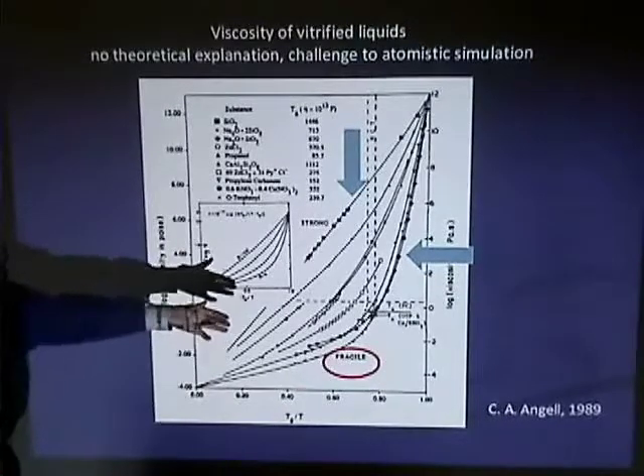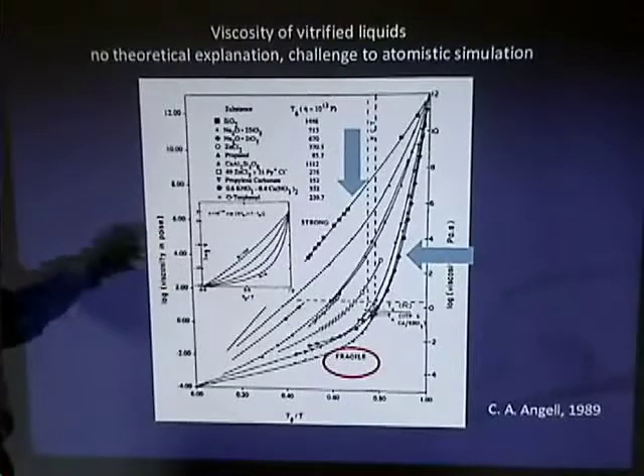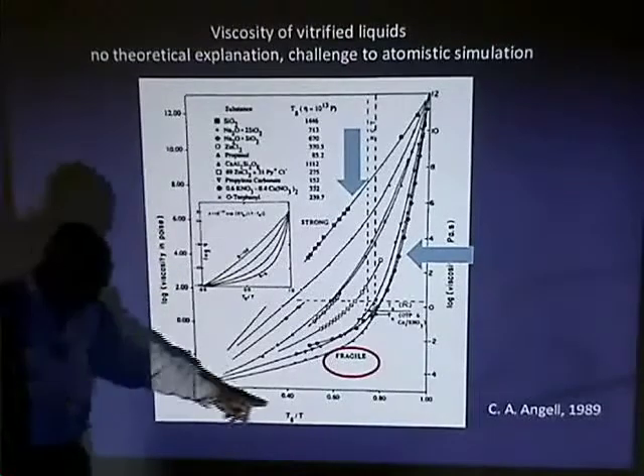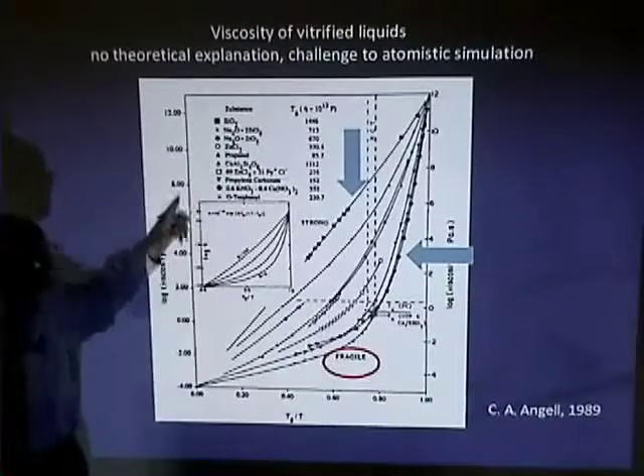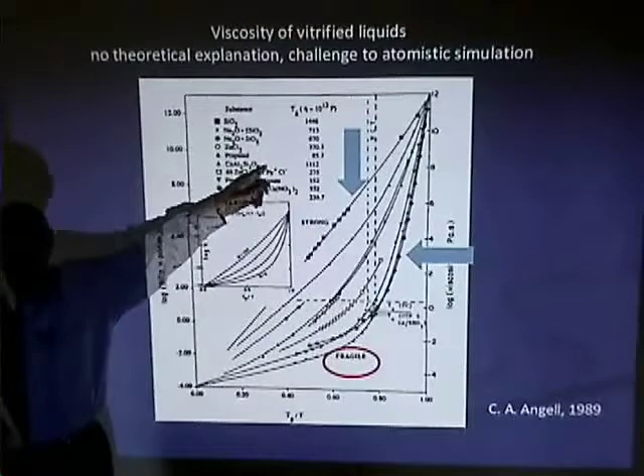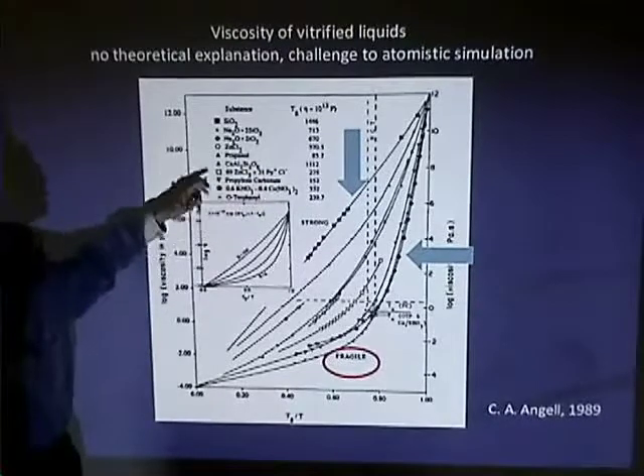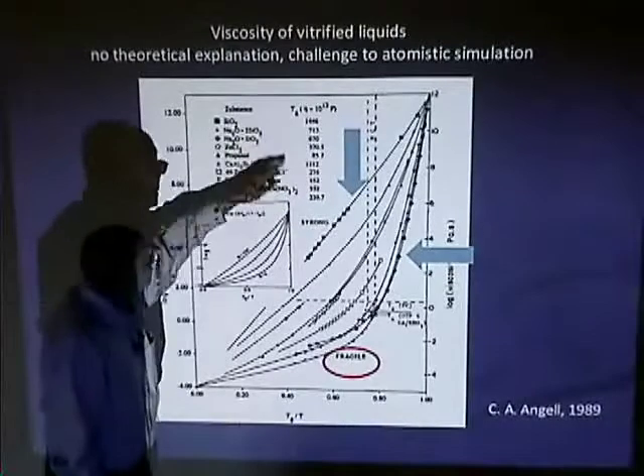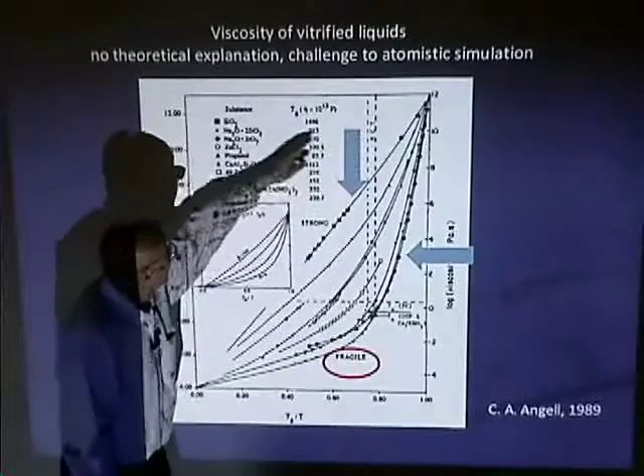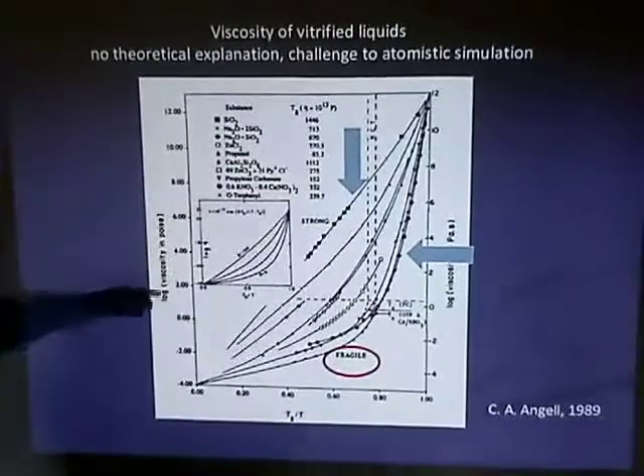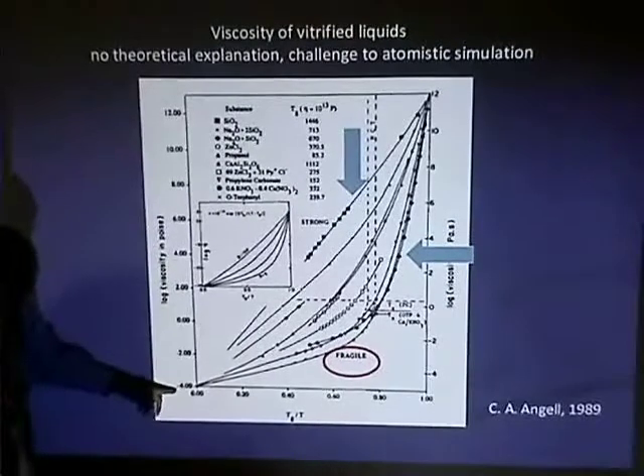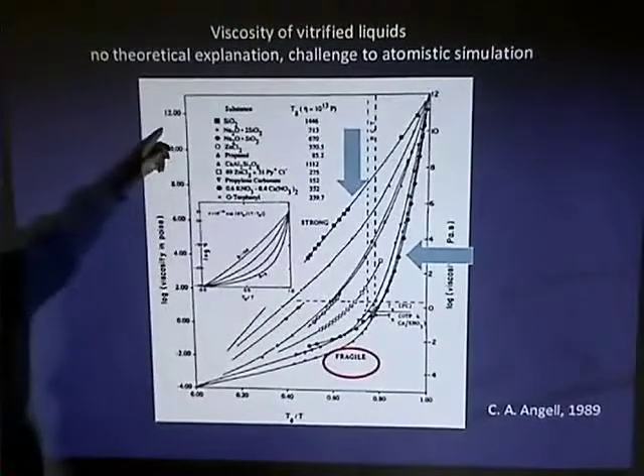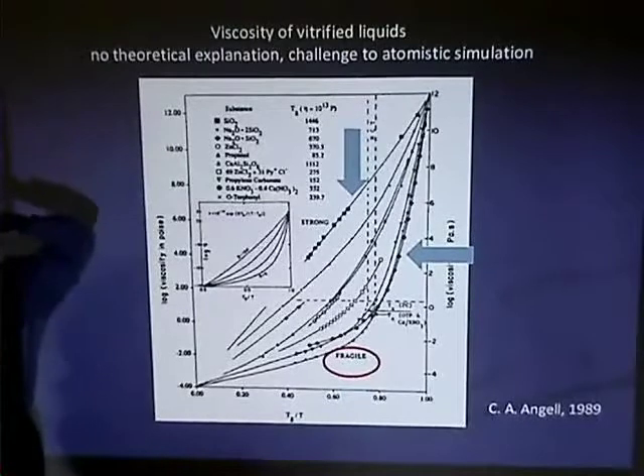Austin Angell in '89 put up such a graph. Cleverly, he normalized the temperature in terms of what he calls TG, nothing more than that temperature where the viscosity is 10 to the 13 poise, or 10 to the 12 Pascal second. So everything is normalized to T over TG, and this is the log of the viscosity. So you go from an exponent of -4 to an exponent of 12, you've got 16 orders of magnitude.